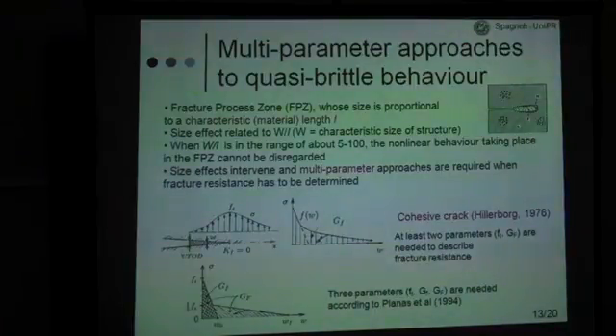One of the very first models used in the concrete community to describe this quasi-brittle behavior is the cohesive crack model by Hillerborg, which needs the use of two parameters. One is the tensile strength, Ft, and the other the fracture energy, Gf. There are many papers in the literature on this Hillerborg paper, and there are refinements on the theory.